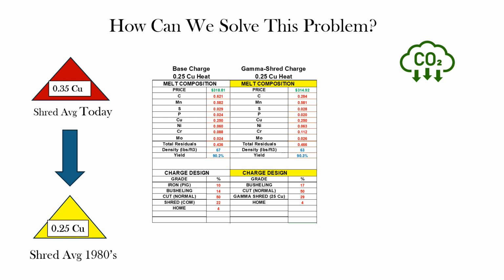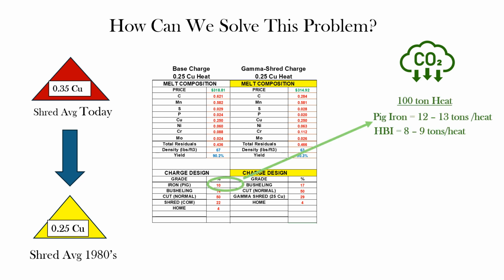And we put that into a linear optimization model. And I'm using a very simple model here. All the steel makers in today's world have much more complex models that deal with slag chemistry, inventory, scrap availability, and steel specifications. But if we put that into this linear optimization model for example, an SBQ heat, I'm able to reduce the ore-based materials by 10%, in this case pig iron, which reduces the CO2 emissions, scope 3 emissions, by 12 to 13 tons per heat, and HBI 8 to 9 tons per heat.